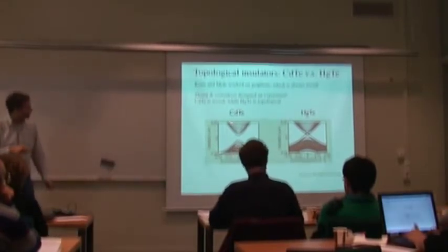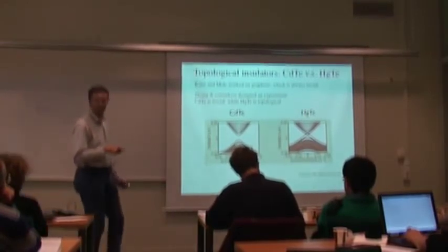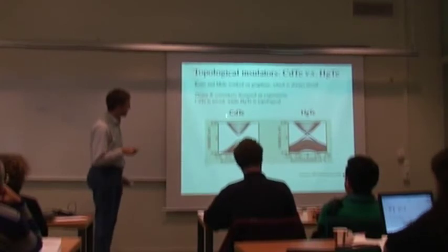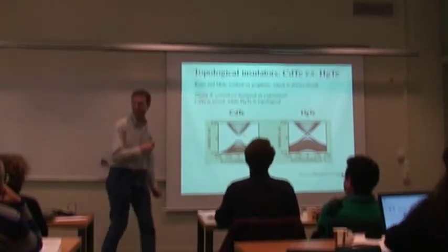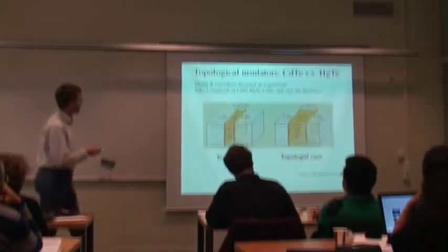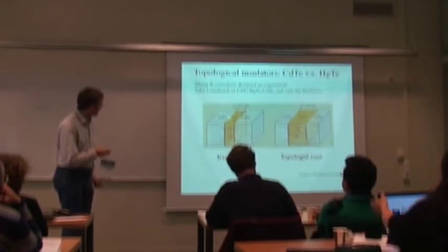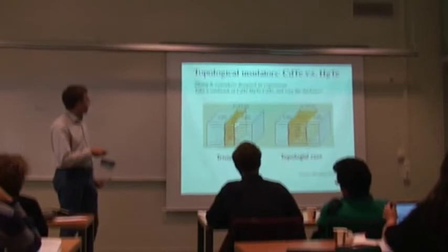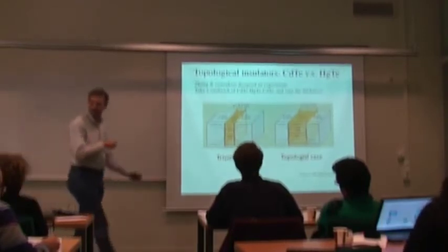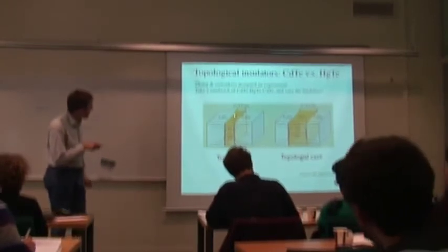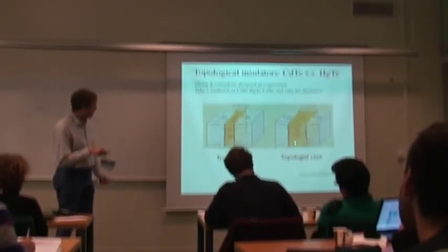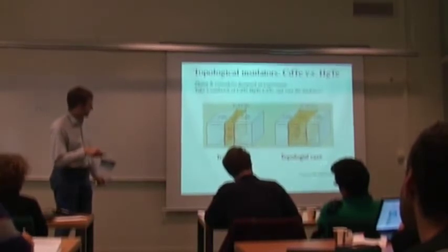Not only did they realize that, they also came up with an experiment of how you can actually distinguish these two. This is where this picture of BHZ theory comes back. Maybe we do a sandwich of cadmium telluride, mercury telluride, and cadmium telluride. The proposed experiment was to sandwich this topological material in between the cadmium telluride. If this layer is very thin, then the whole material will be dominated by the trivial type of behavior. You have to do a calculation to show this. So with a very thin layer of mercury telluride, you will see a trivial insulator. If you make it thicker, then in this region the behavior of the material is such that you see topological behavior.